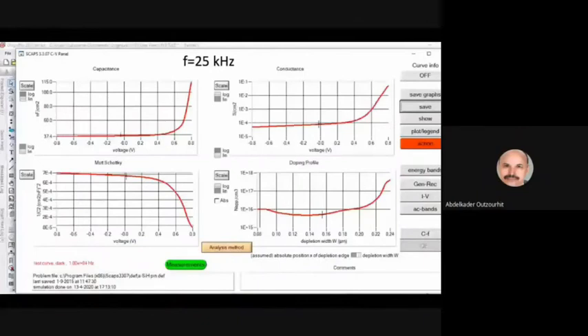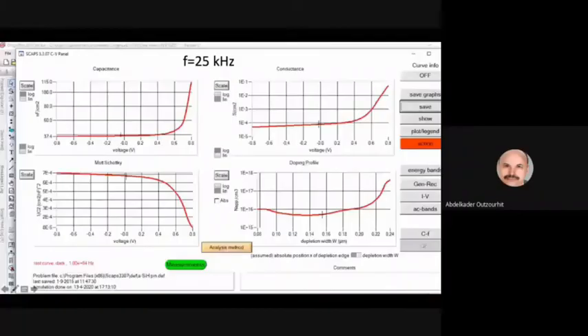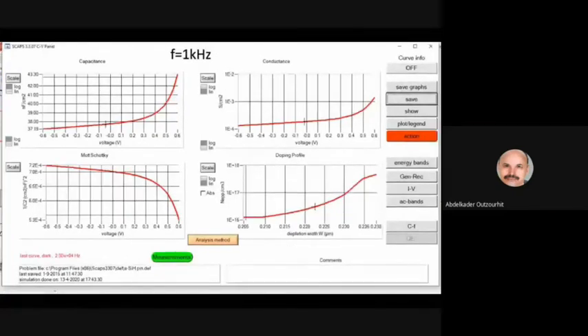As we can see, this is in agreement with the dielectric capacitance of our solar cells, which is only due to the intrinsic layer. We also have conductance here, and the conductance follows the same behavior, increases with increasing forward bias. At 1 kilohertz, the increase in the capacitance is much higher, as we saw in the experimental data. In addition, also the conductance follows the same behavior here.